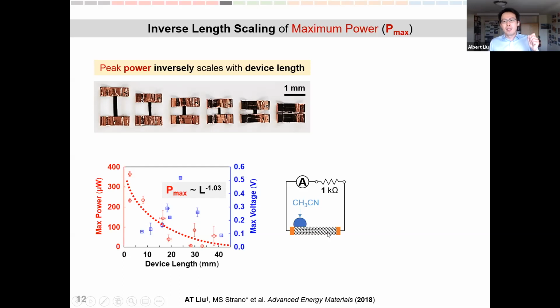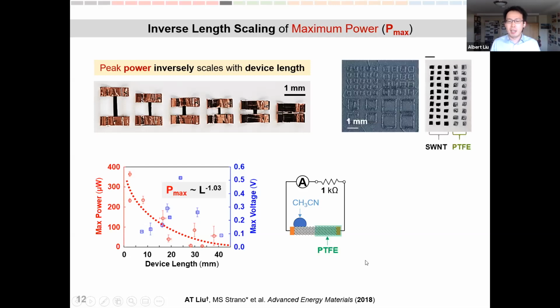So this bodes really well for asymmetric chemical doping to be used as a microscopic power harvesting method. In doing the experiment for very, very small devices, we soon discovered that it becomes really cumbersome for us to drop these acetonitrile molecules asymmetrically onto the carbon nanotube in a spatially asymmetric manner. So instead, what we do is take a polymer protection layer, in this case PTFE, and coat our carbon nanotube in a Janus fashion, making these Janus particles.